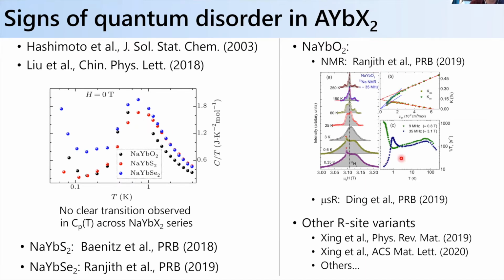And there's also been very nice work looking at NMR supporting the fact that the system doesn't order, that it has a fluctuating state down to the lowest temperatures they've measured, in this case, helium-3 temperatures. There's also muSR data showing that you do have persistent saturating fluctuations at low temperature in sodium ytterbium O2. And there are also other studies looking at other R-site variants. I forget if it's maybe erbium or something. There are a few others claiming that they may have similar phase diagrams as the ytterbium system.